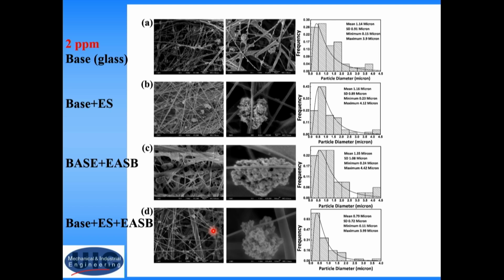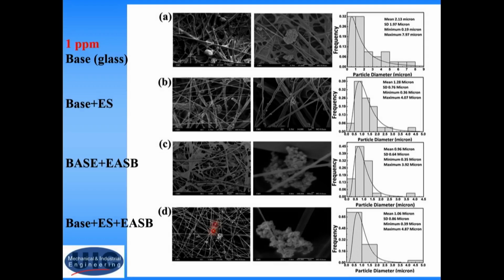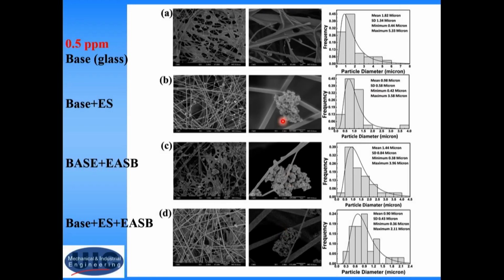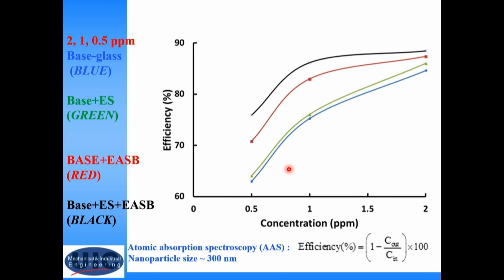So you might expect that the bigger the fiber you put, the better you intercept. But it appears to be just the opposite. The thinnest fibers are the most important collectors. This is some additional information about this type of clusters. And interesting that they can grow behind the filament as well as before the filament. So this is not a totally different structure from the inertial interception, I would say, or diffusion interception. This type of clusters are collected by van der Waals forces. I have many more, because I like them, a lot of clusters like that, very unusual.